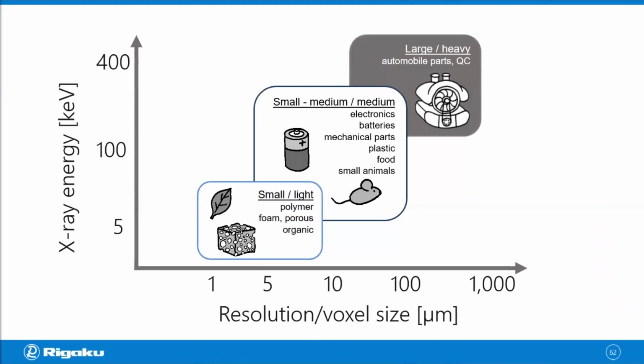The third category is for small and light materials, like polymers, foams, organic materials, including plants and insects. And for that area, you need low energy X-ray source, anywhere from 5 keV to 15 or 20 keV. And because the structure you're trying to image here are often very small or fine, you need a little bit higher resolution, going down to 1 micron or sometimes even a couple hundred nanometers. So that's the third category. And again, those are three major groups or categories of X-ray CT scanners. And one of the major differences between the three is the X-ray energy their sources have.